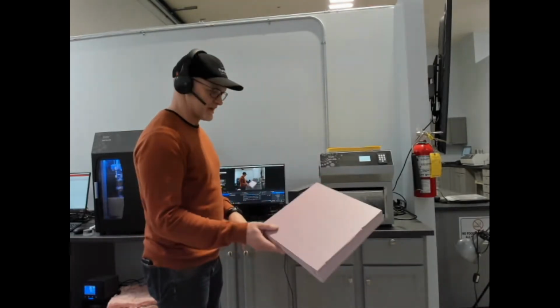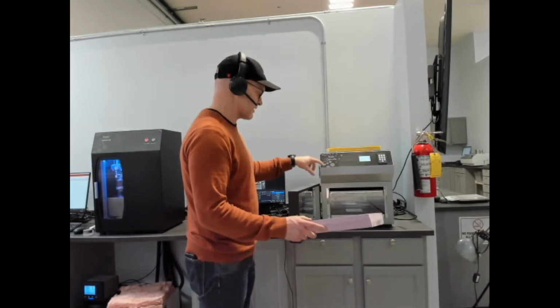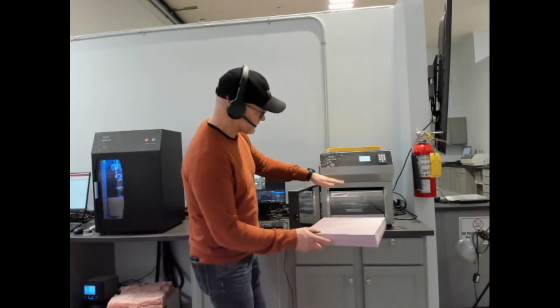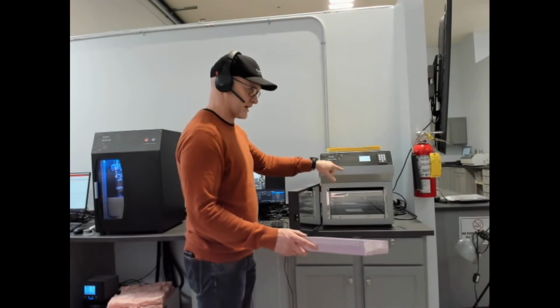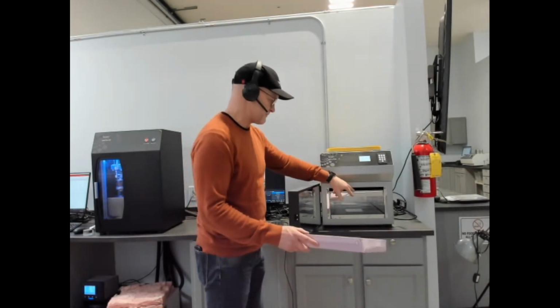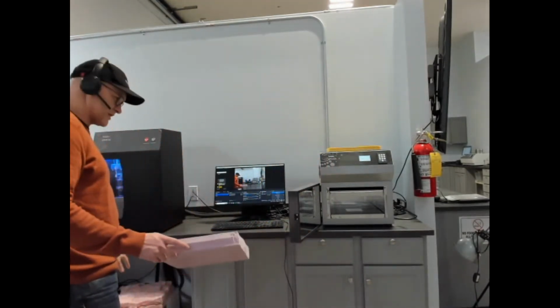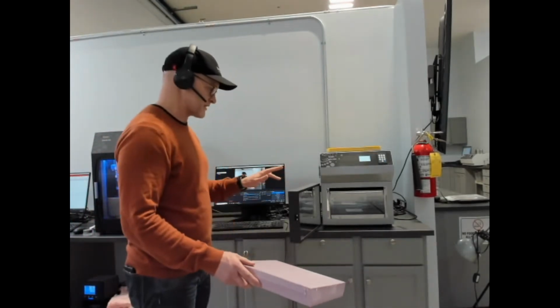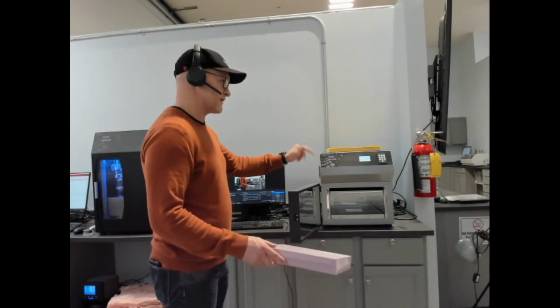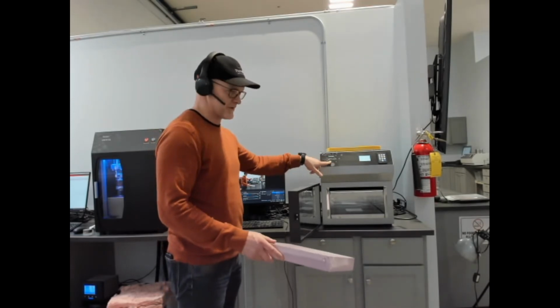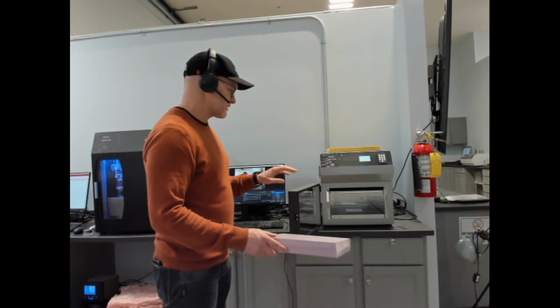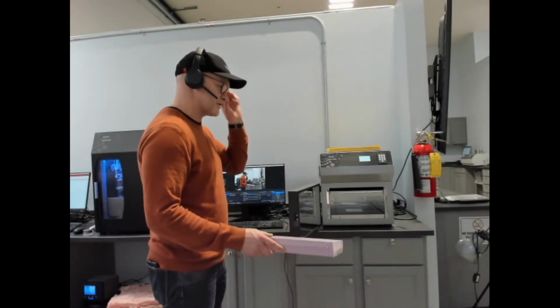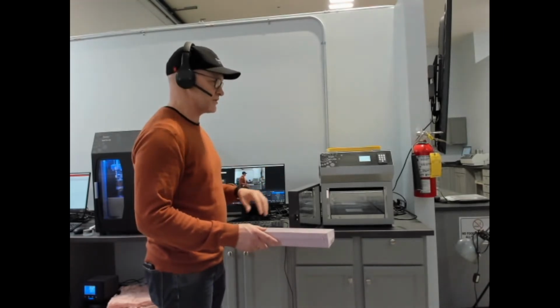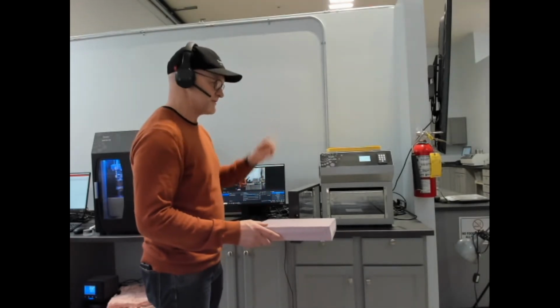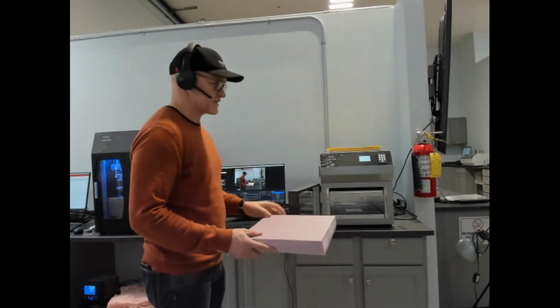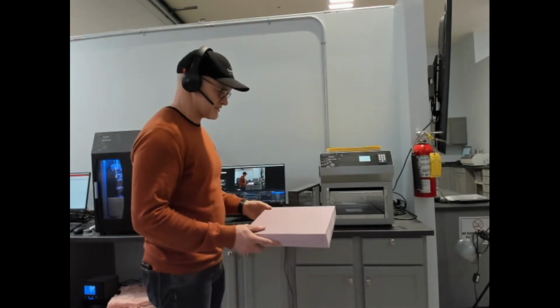For setting up a sample, the flux sensor inside the HFM-100 is 4-inch square, or 100 by 100, and there's one on the top and one on the bottom. All the cooling and heating comes from Peltier tiles, several of them on the back side of each plate. Those Peltier tiles are chilled with a chilled recirculator, which is typically set around 10 degrees. The overall temperature range of the plates is 75 degrees to -20, and that's the same for both the HFM-50 and the HFM-100. The mean temperature range depends on your delta. If you're doing a 20-degree delta, your mean temperature range is 10 degrees inside of that, so 10 degrees below 75, and 10 degrees above the bottom. Your mean temperature range and your delta on each side of that determine the full operating mean temperature.